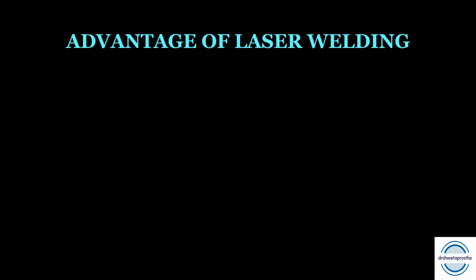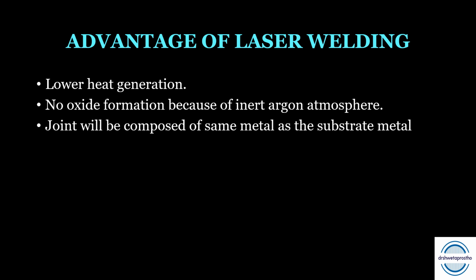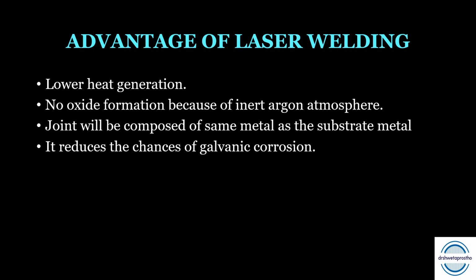Advantages of laser welding: first, there is lower heat generation. Second, there is no oxide formation because of the inert argon atmosphere. Third, the joint will be composed of the same metal as the substrate metal, so it also preserves biocompatibility. It also reduces the chances of galvanic corrosion. Now, laser welding, as I told you, can be done close to the resin or ceramic portions without the fear of damage.